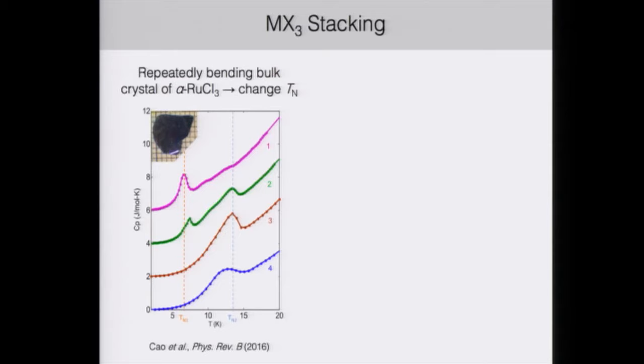There's been a lot of other evidence in the literature supporting that the stacking order in transition metal trihalides is important for the magnetic order. So in this one paper published a few years ago, they took alpha ruthenium chloride bulk crystals, which are similar in structure to the chromium trihalides, and they repeatedly bent the crystal back and forth. And what they found was that with successive bending, they were able to shift the Néel temperature from 7 Kelvin up to 14 Kelvin. And they attribute this to introducing stacking faults between the layers in this bulk crystal, which one can think of as similar to the mechanical exfoliation process of our bulk crystals as we cleave them down to the few layer limit.